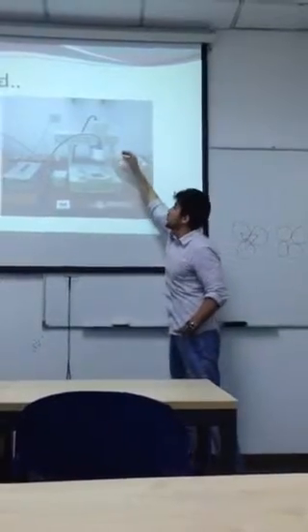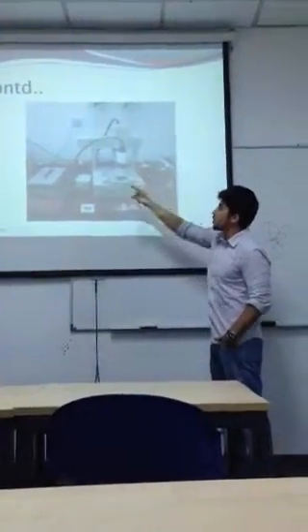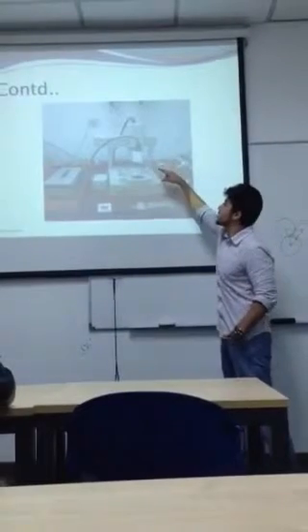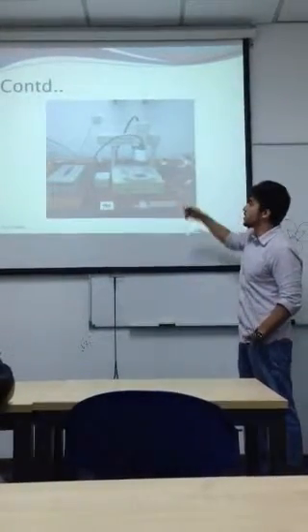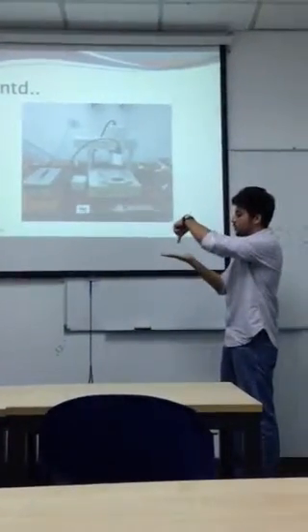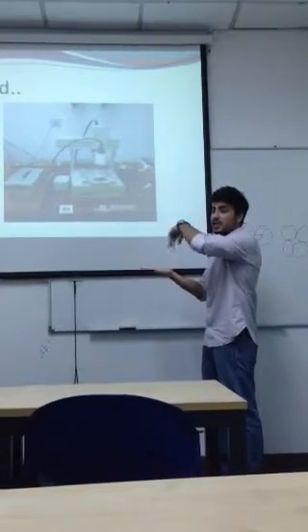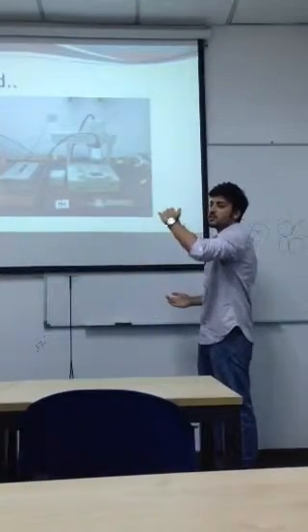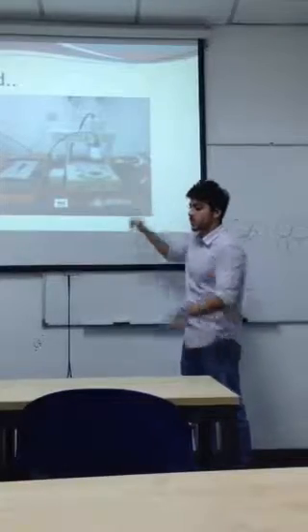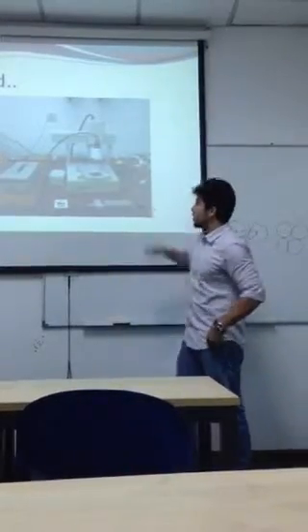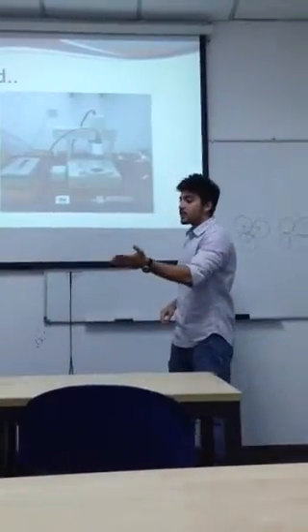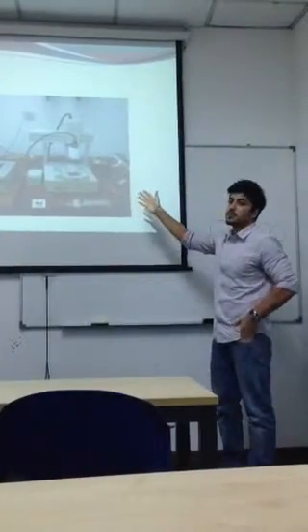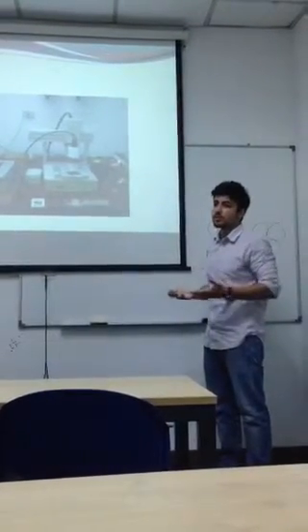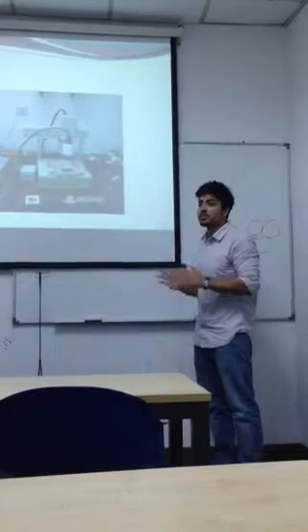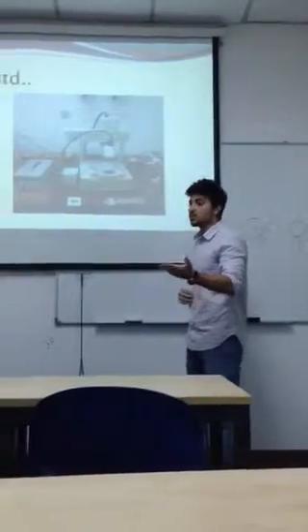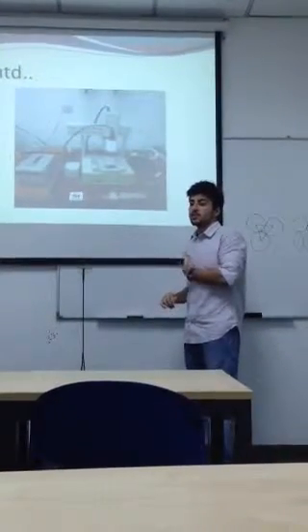Basically the polymers are inserted in here, controlled by pressure, the pressure vessel, and the heating. These polymers are ejected. The polymer just goes down, ejects the polyfilaments in the X, Y direction, and then gradually the Z direction is for the layers. So this is how you can fabricate these scaffolds. And the really advantageous thing of 3D plotting is your interconnectivity is 100% in comparison to others. You have 100% interconnectivity. And studies have shown that the porosity level can reach up to 86%.